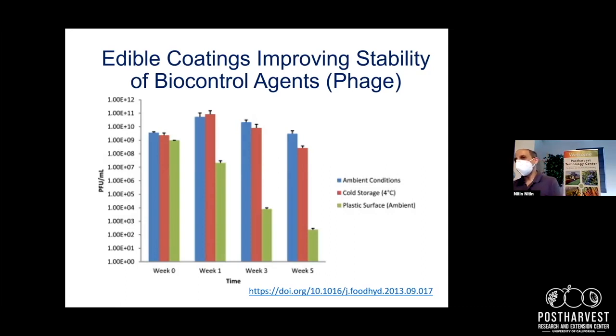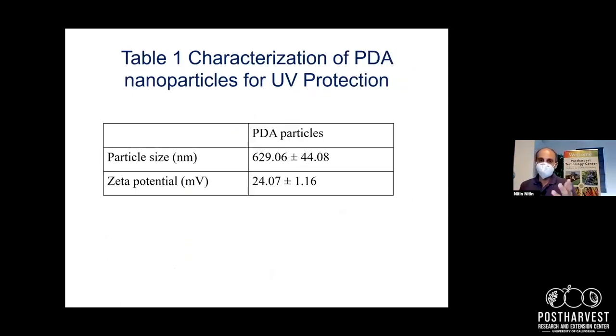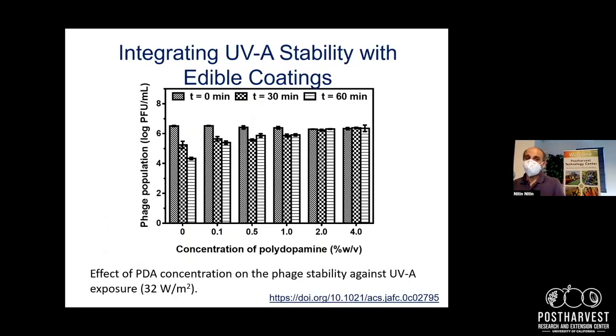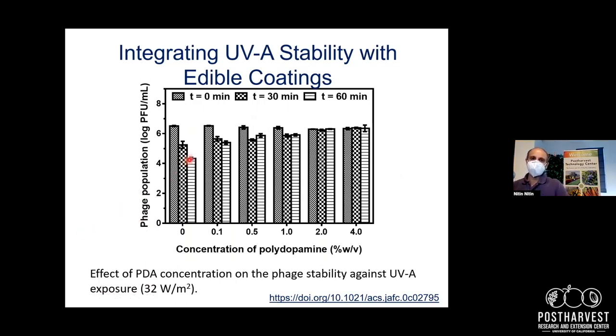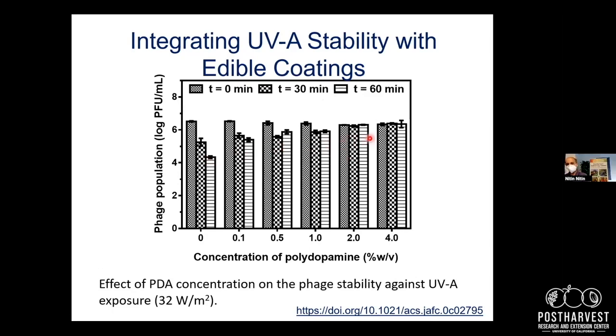And the same concept could be extended to other microbes which are susceptible to decay, but may have a biocontrol perspective on them. We designed some polymer particles using food grade materials, dopamine. So these are polydopamine particles which were designed to maintain the UV protection properties. So we added those to the film. And as you can see, even a very short period of UV exposure can result in about 2 log inactivation of these phages. And we looked at whether, if we add a small amount of polydopamine particles, we can preserve the activity of this biocontrol agent for an extended period of time against UV in this case.